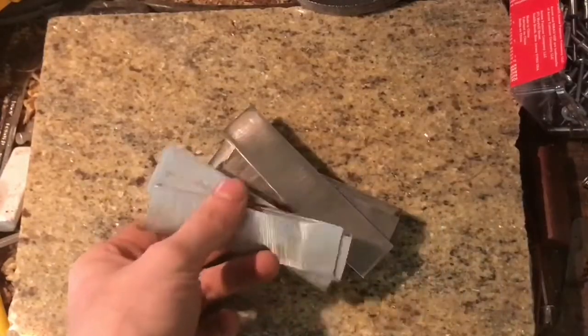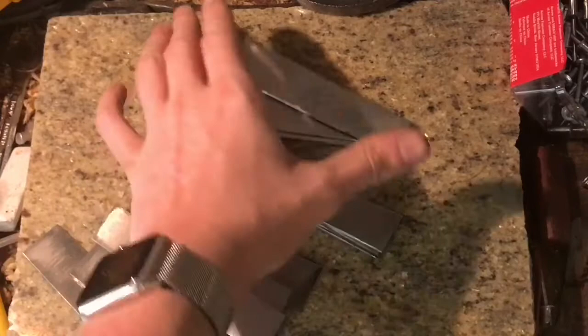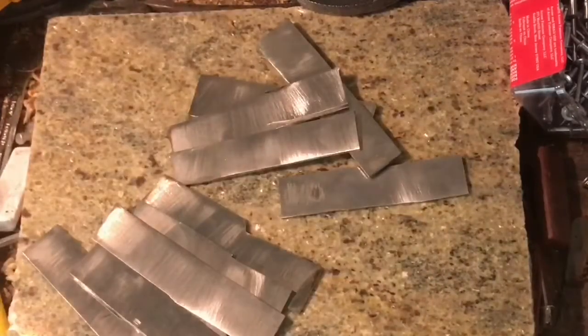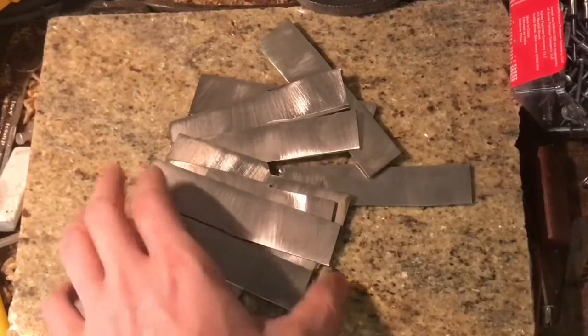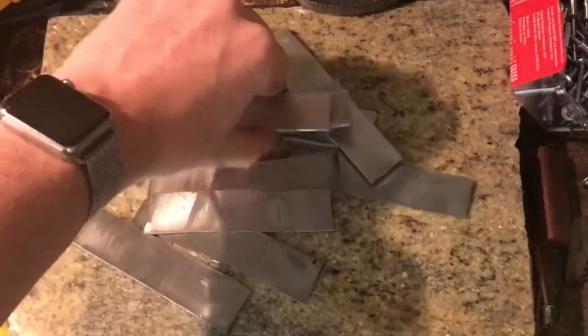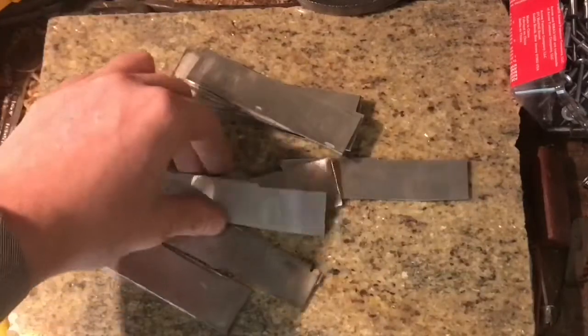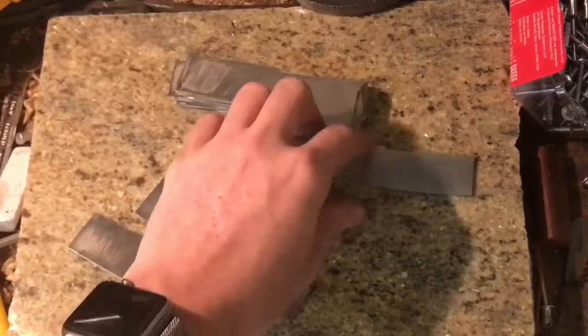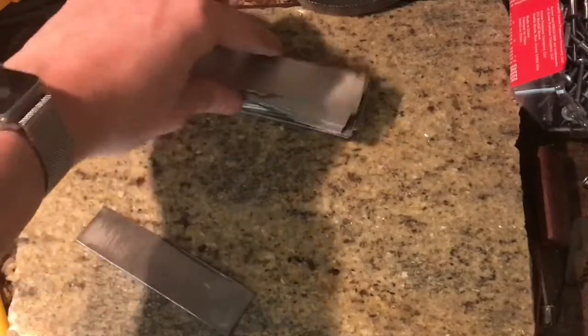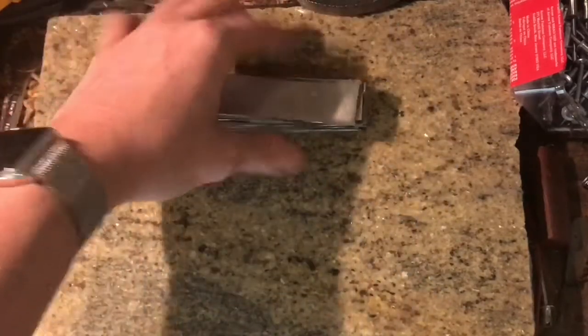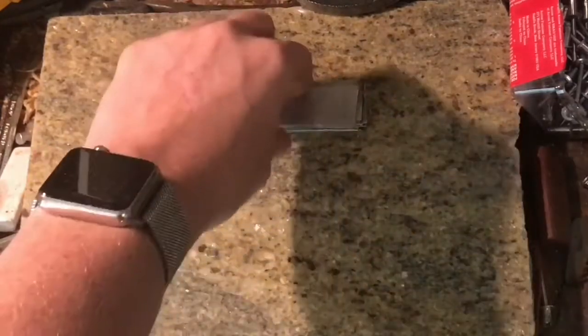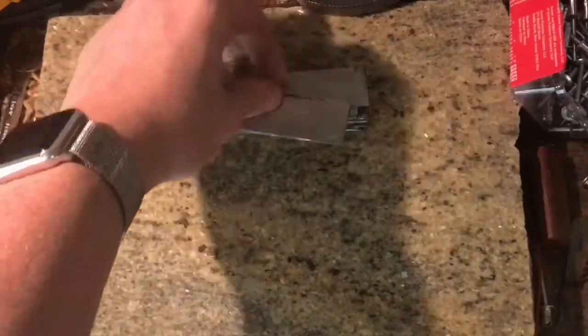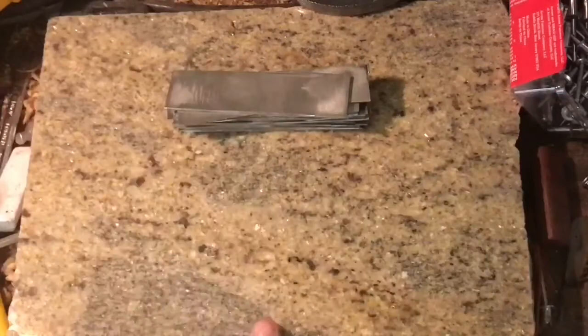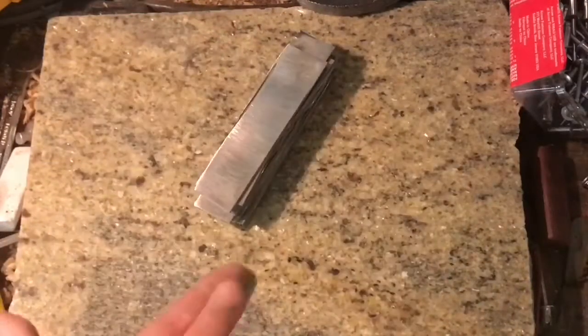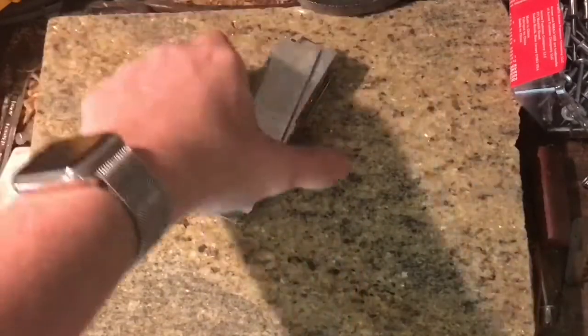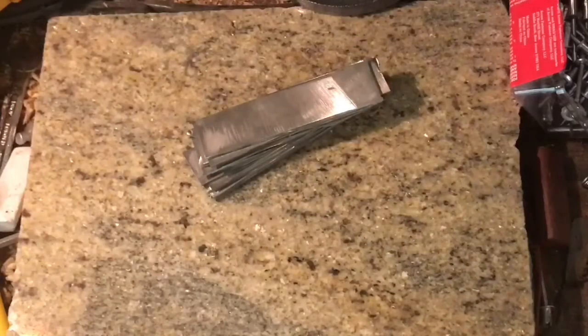Alright, so now I have the freshly ground pieces of flat bar ready to be tack welded along the sides. The reason why you do that is so they stay together in the fire before you actually deliver the hammer blows to set them together. We're actually just going to do that with an arc welder. Well, we're going to forge weld with a hammer, but tack weld the sides and probably weld a handle onto it too, so we can hold it. We're going to do that just with a DC arc welder.